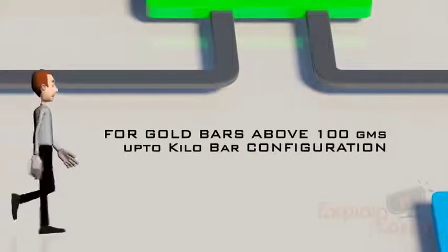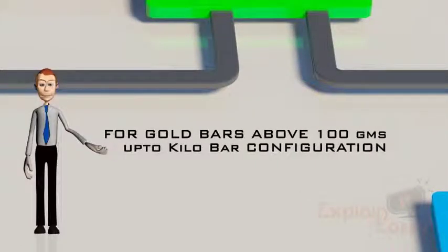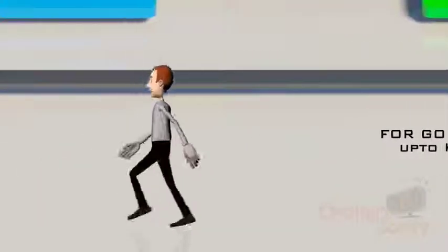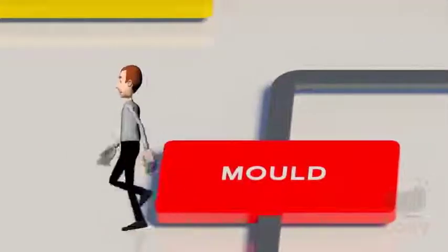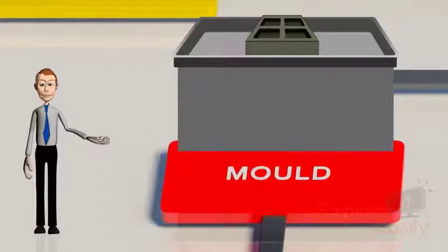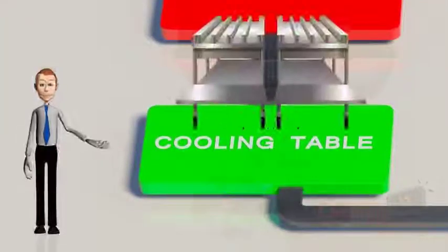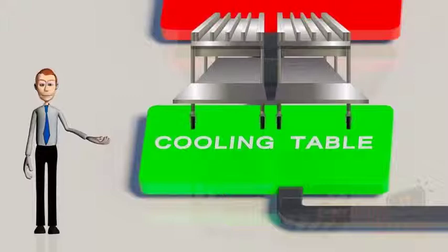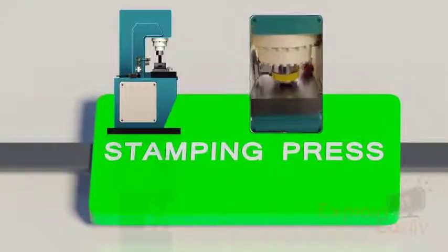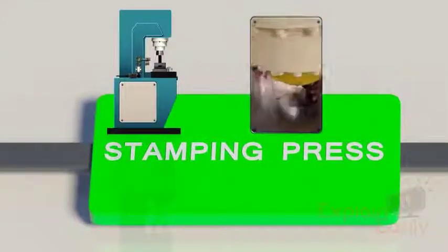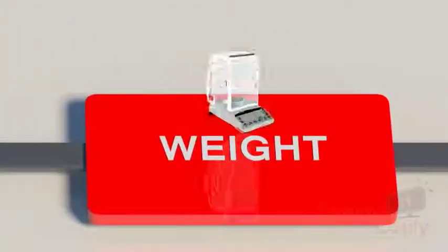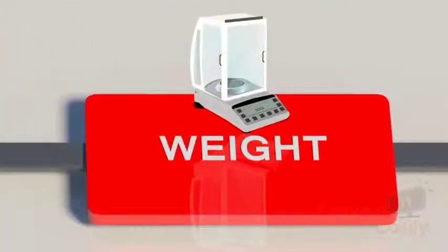For gold bars above 100 GMS up to kilobar configuration, the molten gold is collected in a pre-designed mold for the desired configuration. This is then cooled in the cooling table where bar is formed. A burner flame is used in order that oxides are not formed. This is mainly an annealing step, and then the gold bar is cleaned. The shining gold bar is then put on the stamping press to number and configure the desired mark or logo. At all the steps, weighments are done and adjustments are done by filing to suit the exact weight.